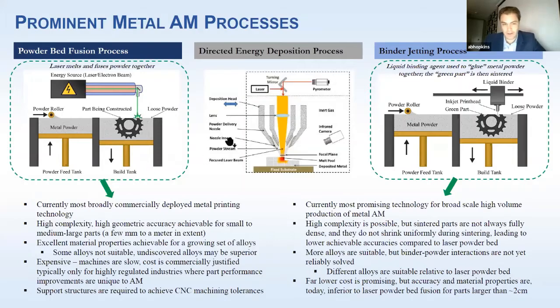You seek to fully melt in laser powder bed fusion, that circle, and then you drop the build stage, spread more powder on top, and do it all over again. At the end of the day, you've got a part sitting in a bucket of powder, fully ready to go, possibly with some residual stress. Great. What are the advantages of this technology? It's very highly accurate, but you do have to deal with residual stress warpage as the part cools. But you can meet machining tolerances in many cases, provided you're properly supported. That's a big deal for the industry because almost every complicated assembly of parts is in fact specified to CNC machining tolerances. So you really want to meet those or come close to them so that you don't have to take your part out of the build bed and throw it into a CNC because that's very expensive.